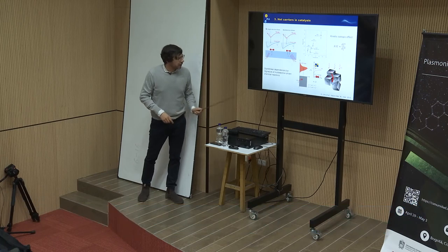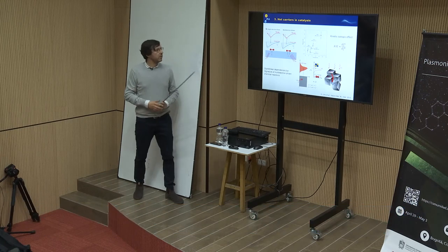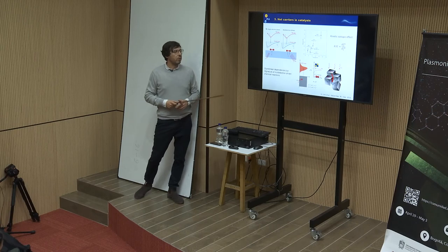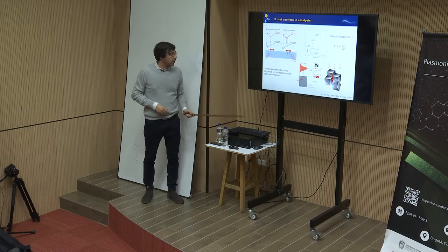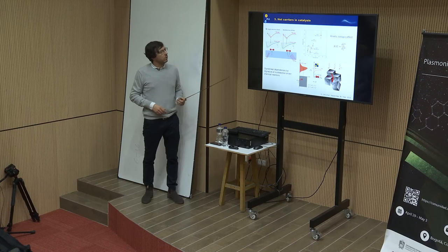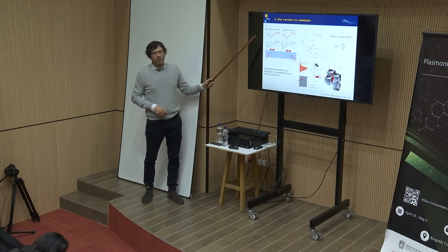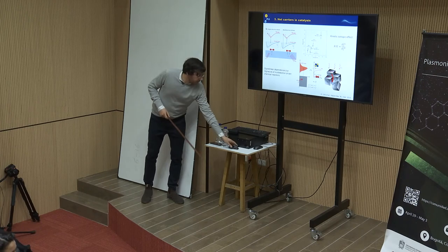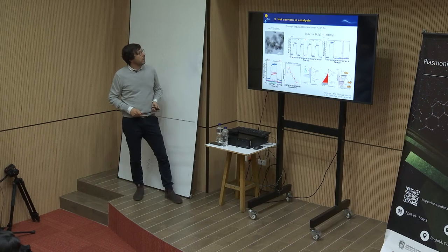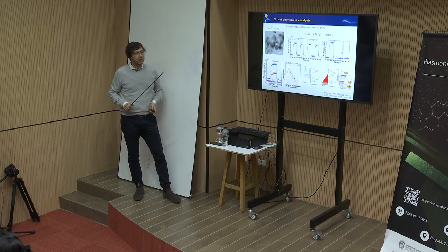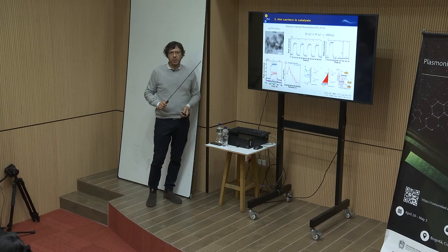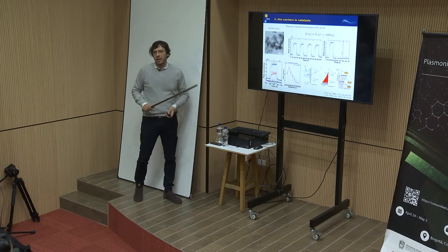And so this is just to say that what they observed, by increasing the intensity of light, was really a different dependence of the production rate of the products as a function of the intensity. And this was attributed to the switch from a single-electron driven mechanism to a multi-electron driven mechanism. So this is also famous. I want to talk about this because this is a famous article which also really brought a lot of interest in this field.